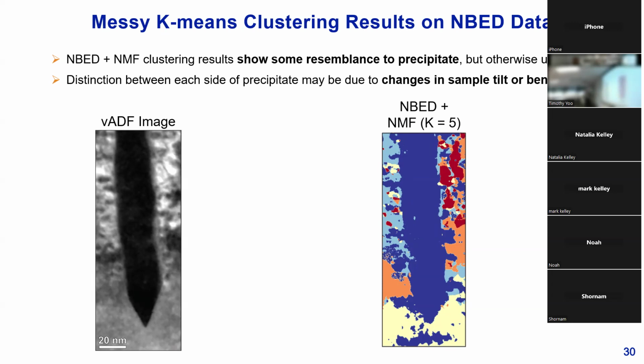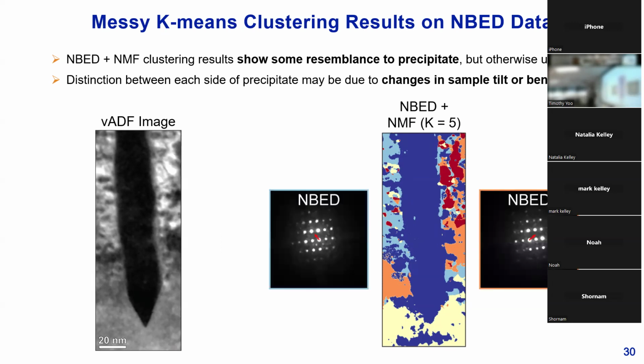We also see that the dark blue that appears to outline the precipitate 1 sort of bleeds out into other regions around it, which again doesn't really make a lot of physical sense if that's truly supposed to represent that precipitate 1 structure. If we take individual diffraction patterns from the left and right side, say one from this light blue region here and one from the orange region, we can see that the intensity distribution is non-central symmetric. We're sort of leaning towards opposite sides of the image frame as marked by the direction of these red arrows here. And so what that tells you, at least in terms of electron diffraction, is that the non-central symmetric intensity distribution is going to be indicative of local sample tilting or bending.